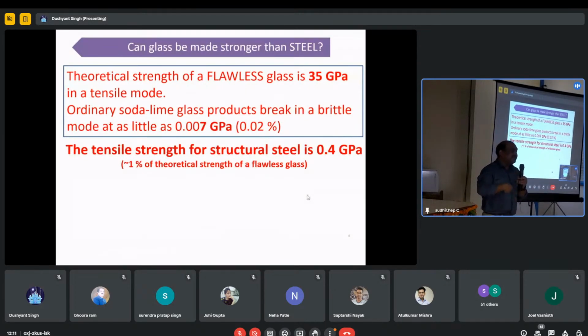But we don't get that kind of strength because glass has small micro cracks all over the glass surface because of handling. If you can achieve 1% of the theoretical strength of glass, you can have a glass as strong as steel. So glass can be easily made much stronger than steel, and there is potential. That's why Gorilla Glass is upgraded. Now it is the 7th and 8th generation. Gradually they are upgrading and making much stronger glasses.